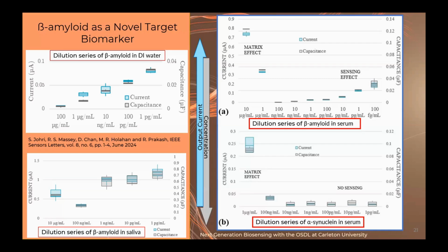So from the very concentrated serum to 50, 100, 200, up to 1,000, 2,000 times diluted serum sample, and we looked at our sensitivity. And as you can see, for the relevant concentration range, we are in the sensitive region. We do lose sensitivity, and it becomes predominantly matrix effect because of the surface area being saturated and the solution being too inundated with competing HSA and other proteomic markers. But thankfully for us, this is the region of interest where we have been sensitive in serum and saliva, as the testing show.